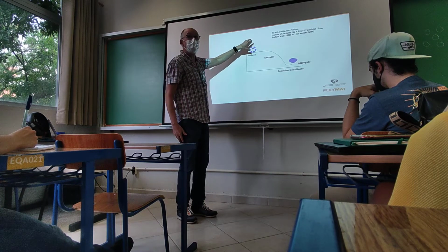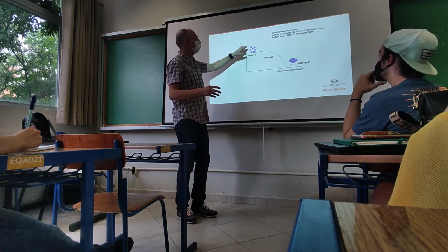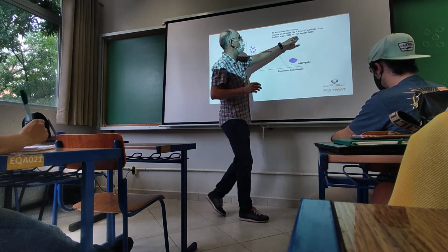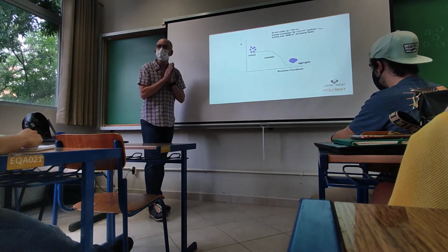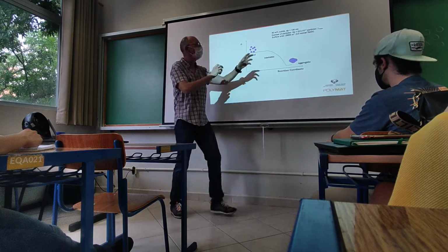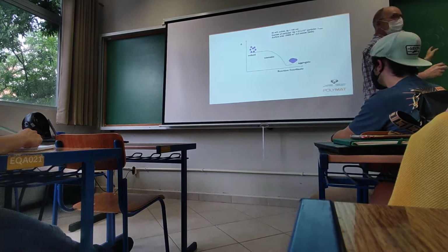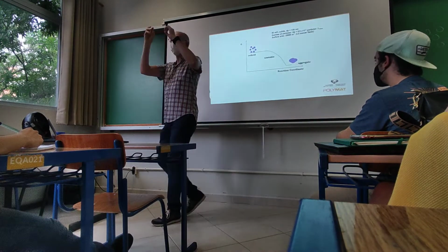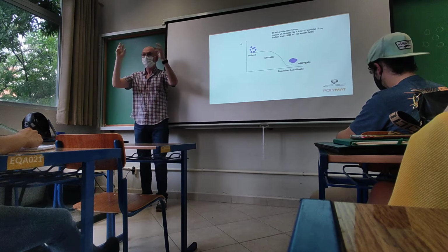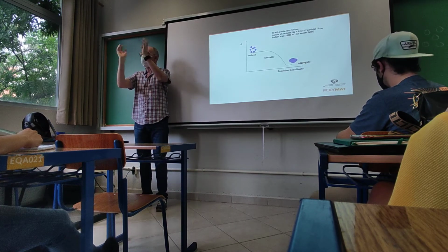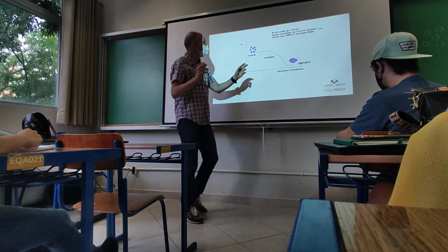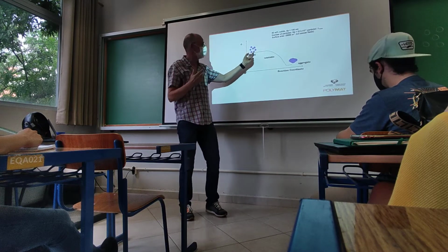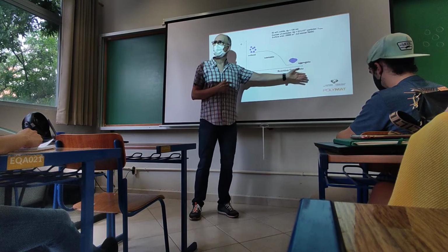The dispersion of particles that we create, as we discussed, has a huge surface area. So we said that 2.5 square meters per liter of latex. So this dispersion of particles is thermodynamically unstable. So they cannot stay stable. Due to the Brownian motion of the particles, because of the temperature, if they approach, they will coagulate. So thermodynamically, a dispersion like this, with these characteristics, is totally unstable. So it will aggregate. Okay?